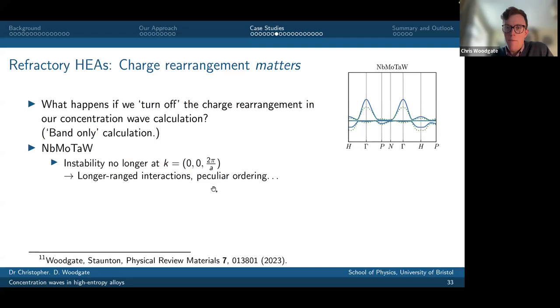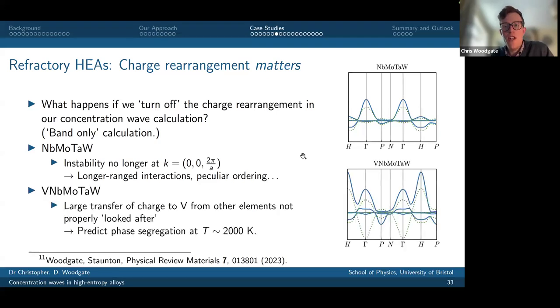The real kind of failure of the band-only approximation, though, is in this 5-component alloy where there is this substantial charge transfer between vanadium or to vanadium from the other elements. And there, what you find is if you run a band-only calculation, you predict that the system phase segregates at something like 2000 Kelvin, which is completely at odds with reality. So it turns out that if you're going to do these kind of concentration wave-like analyses, in any system where there is any kind of reasonable charge transfer between the alloying elements, you really need to consider how the charge rearranges itself in response to an applied chemical fluctuation.